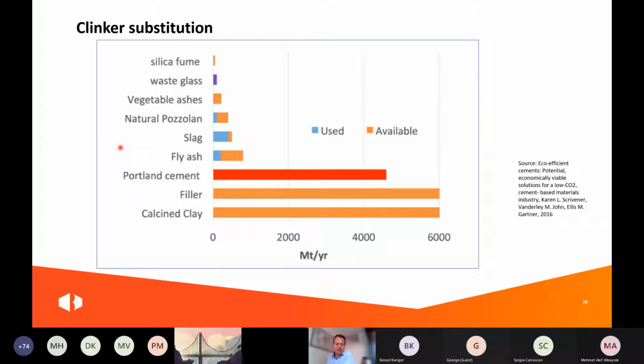But what we can have in the future as well is, of course, filler. This is limestone. We can produce that without any limit, and we can calcine clay, and then we have, of course, also a limited availability of clay. And that's not currently done because we still have sufficient slag available, although only about 8% of the total cement production. But you will see that in the future more and more calcined clay will be used to reduce the clinker content in cement.